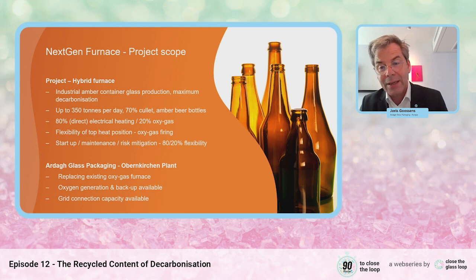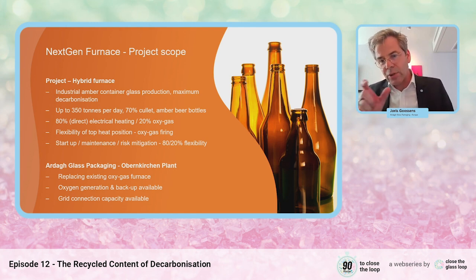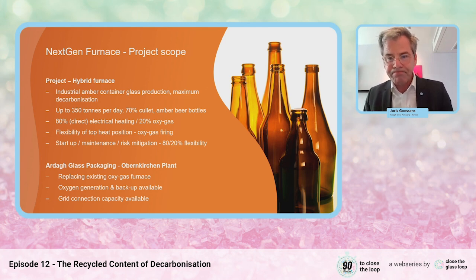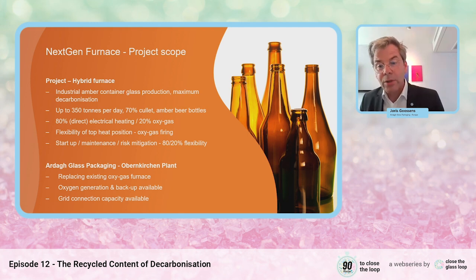And the limit we think in this new design is 80% electrical heating. We still need 20% radiative flame heat, so 20% oxygas in this new design. And we chose oxygas because in oxygas you are quite flexible in your burner position. So there is some flexibility there. On top of that, we have flexibility to switch between 20 and 80% electrical heating and vice versa, 80 and 20% oxygas. And this is because we wanted to start up the furnace as conventionally as possible. And we also do it as a risk mitigation. It's a new technology, so we're not sure it works over the entire range, so there is some mitigation there.